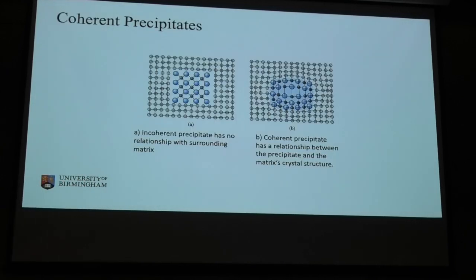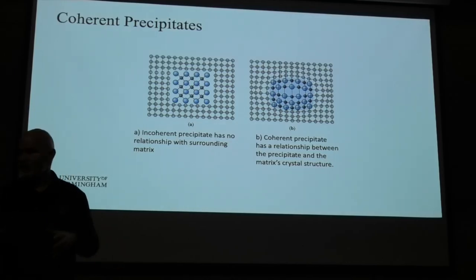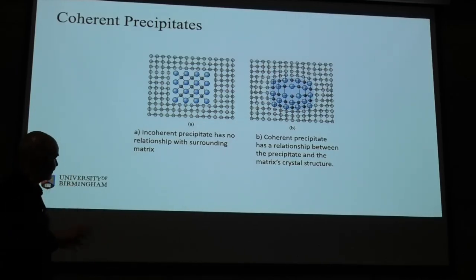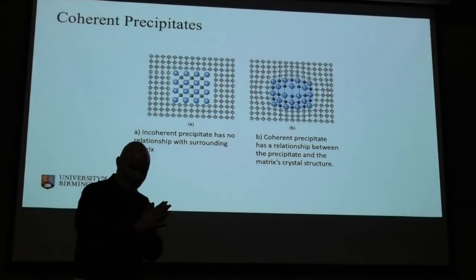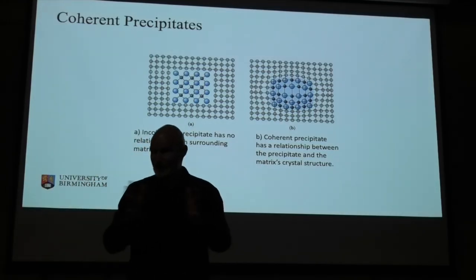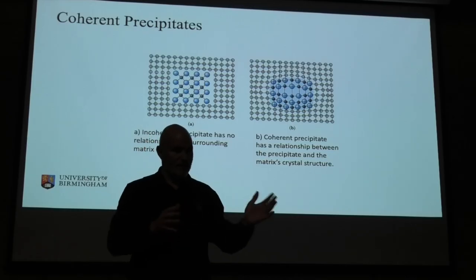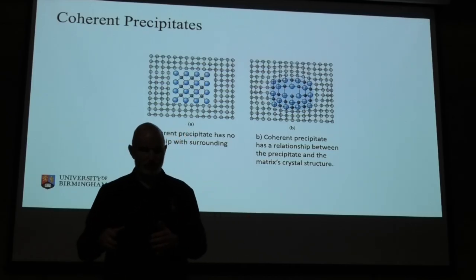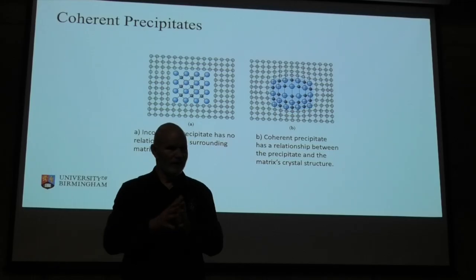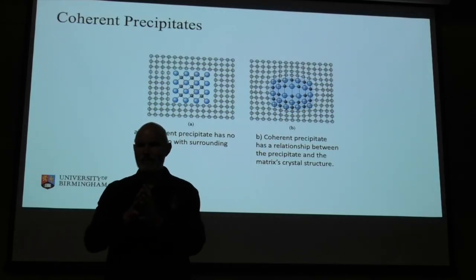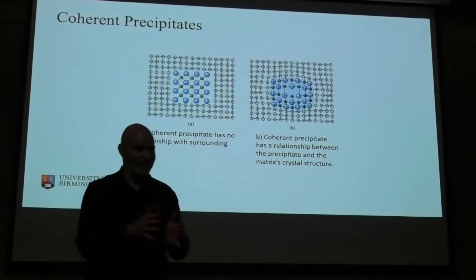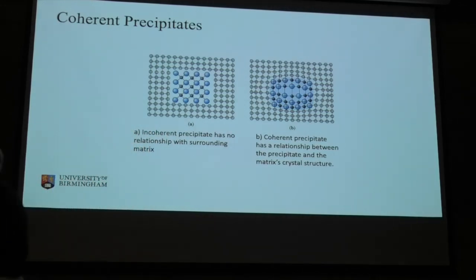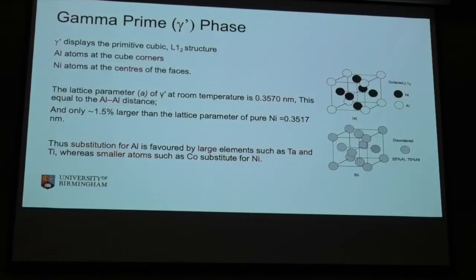What this means is they come out as a precipitate, but it's called coherent - it's actually exactly the same crystal structure, just ordered rather than disordered. There's a slight mismatch, maybe in the spacing of the atoms, but only a few percent. So it sits there in the crystal lattice, and the atoms themselves think they're in the same crystal. There isn't a boundary, so we can't get sliding because there isn't a boundary that they've noticed - they can wander to the next atom and it just carries on. So that's really nice, we get these ordered precipitates.